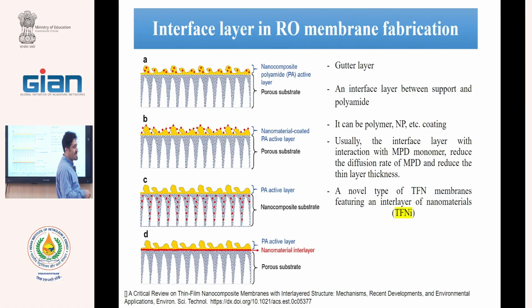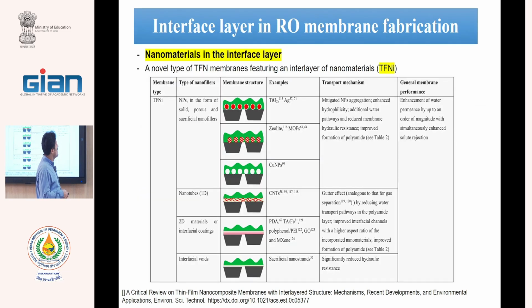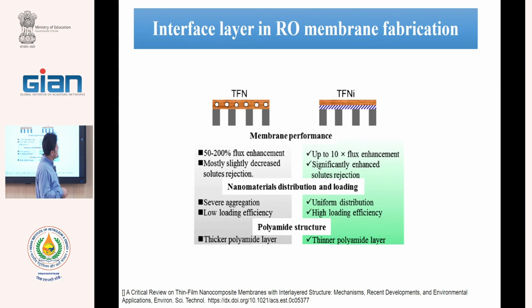This layer can be nanomaterials, can be another polymer, such as polydopamine, polyvinyl alcohol, and others. That in this slide shows that most use nanomaterials for as this gutter layer or interface layer. And in this slide, compare the traditional membrane with the interface layer membrane, and we see that with using of this interface layer, flux can be increased 10 times.